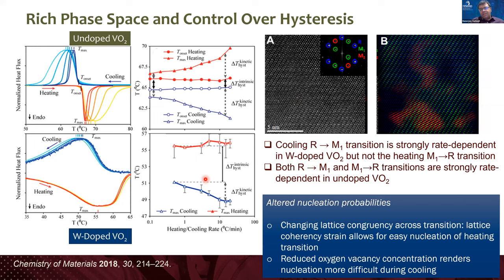We find, interestingly, very distinctive behavior going up and down. So the forward transition versus the reverse transition. So we've been able to identify these M2 phases that form that are strain stabilized. And these, as well as the phase boundaries, are where the transition nucleates on the way up. And so there is not a very large kinetic component to the forward transition, but there is more of a kinetic component to the reverse transition.